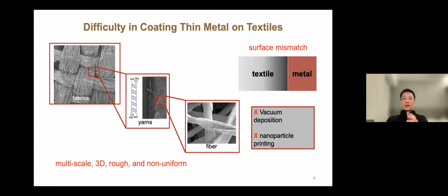We have been doing metal deposition on textile for more than 10 years. It was very difficult at the very beginning. The reason is that the textile material we've been using, either carbon or polymer-based, has a huge difference from metal in terms of surface energy, thermal conductivity, thermal expansion, and mechanical modulus. They differ by a factor of 1,000 or 10,000.